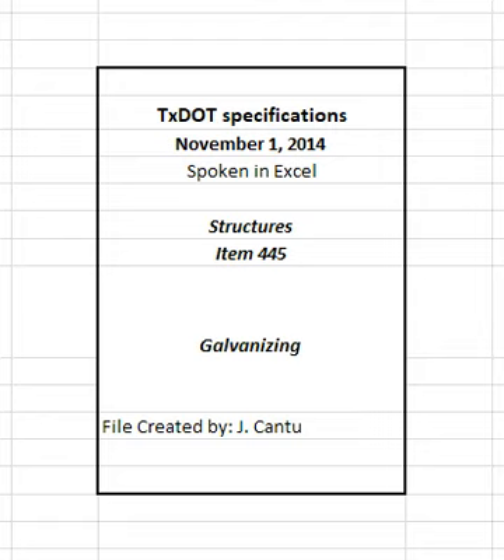3.4.2 Adhesion. Tap the coated area with a small hammer to test coating adhesion. The coating is acceptable if it is not brittle and does not scale or flake. 3.4.3 Appearance. 3.4.3.1 White rust. A white powdery residue indicates moisture. Remove heavy layers of white rust that have caused the coating to pit. Light coatings may remain unless the engineer requires chemical removal. Remove white rust from articles that will be in direct contact with soil.